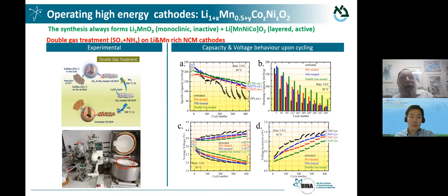And this gas treatment, these gas treatments affect the surface. We have surface reactions, and we have chemical changes of the surface. We have sulfate networking on the surface, and by the reactivity between the gases and the surface, we form a buffer zone, we form chemical passivation, that isolates, and it's still an SEI, a solid electrolyte interface. It allows lithium ion transport, and we see